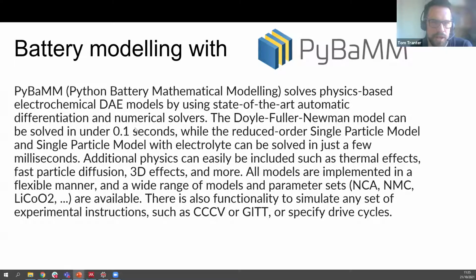But we can solve that model now in less than a second for a single battery, which is a one-dimensional model, and we can resolve essentially the lithium concentration within the cell, and also the temperature and the potentials within the cell. And we also have some even faster reduced order single particle models, which can run in a number of milliseconds. And with this framework, we can replicate all of the cycling experiments that you might do in the battery lab.